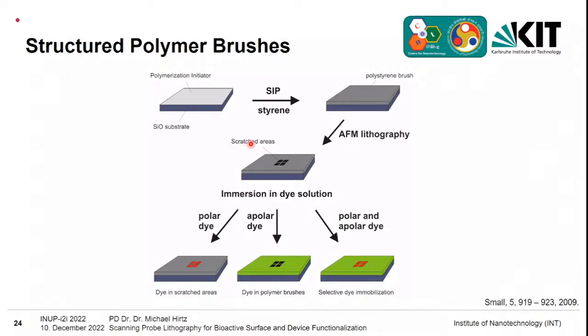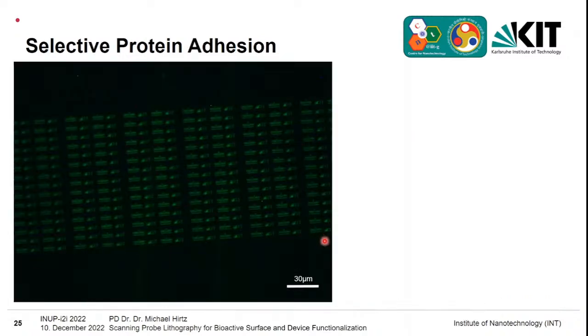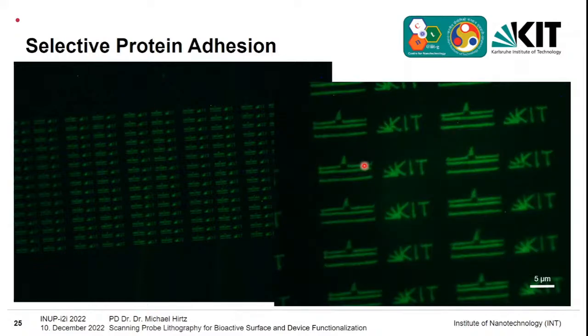You can also use this to get into some proteins, for example, that can assemble directly on the scratched areas, because now you have a chemical contrast between your polystyrene brush and these scratched areas. So here, this was done with a fluorescent protein, and you can see that while the polymer brush around it is fairly dark, it's still selectively attached to the sites that were scratched. And so by this means, you can again get your bioactive patterns.